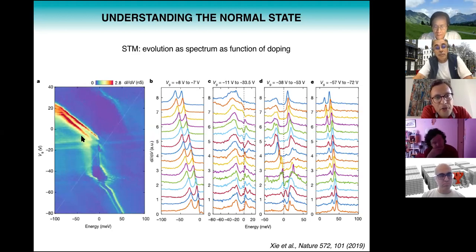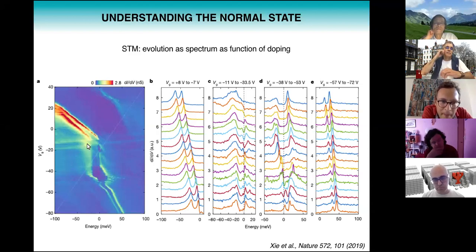So they're showing you, as a function of doping, the evolution of the tunneling spectrum. What you see here is basically this first region where you see the linear dispersion. That's when the flat bands are completely filled, and you get two peaks that just move basically because the Fermi level is changing. Then, however, once the Fermi level hits the high energy Van Hove singularity, the spectrum stops moving. And what this means is you get Fermi level pinning.